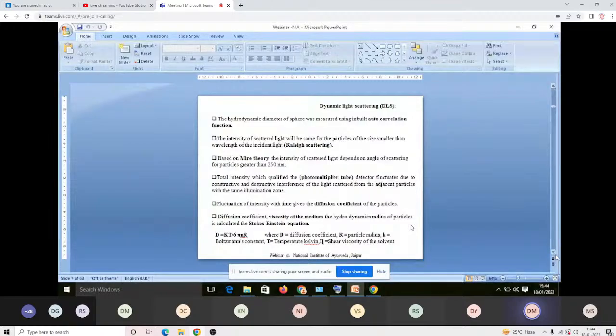Sometimes the intensity of scattered light, when particles are smaller than the wavelength of incident light, you can see the 600 nanometer, that is Rayleigh scattering. Based on Mie theory, the light depends on the angle for particles greater than 250 nanometer. And a photomultiplier tube is the detector. And the fluctuation of the intensity over time gives the diffusion coefficient of these particles.